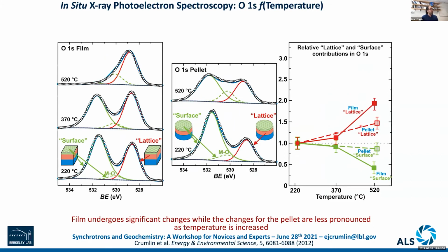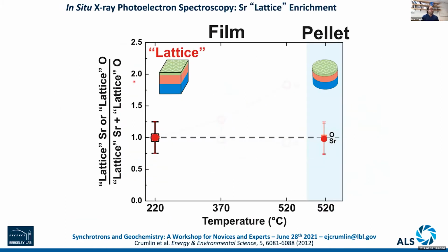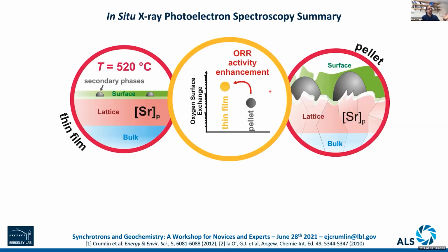We can also see properties changing with the oxygen 1s between the thin film and the pellet, how a surface species is decomposing while the lattice is getting much larger and more prominent. When we bring all this together, it makes it very clear to us how much enrichment of the strontium is taking place on the thin film. So this gets us to see how environmental conditions between gases and temperature can modify significantly the samples that we're looking at. And this gives us a kind of a high level view of what's there.